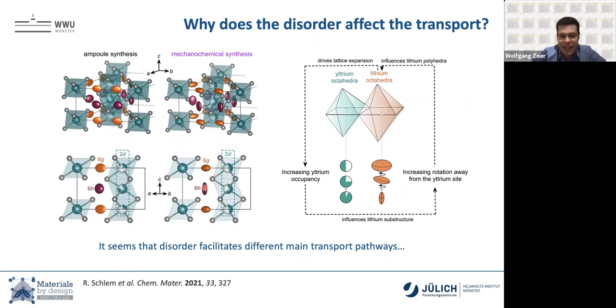So what we're thinking is that by disordering, by moving yttrium down from this side to this one here, there's a little bit more repulsion on some of the lithium, and it just pushes it more in the Z direction. And so the ampule materials, they're mostly diffusion in plane. And as soon as you have this disorder, you actually get three-dimensional diffusion. This is our current working hypothesis. If this is true, this is something that we'll have to figure out in the foreseeable future.